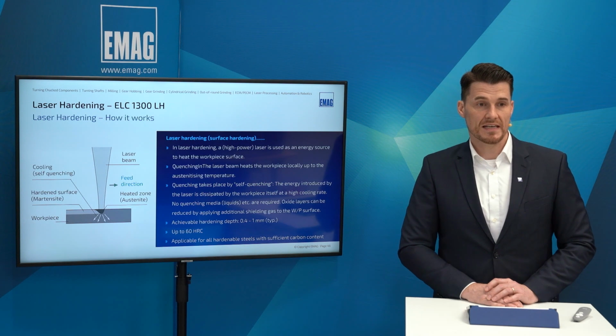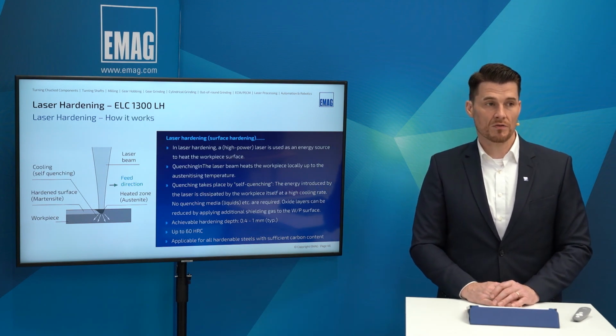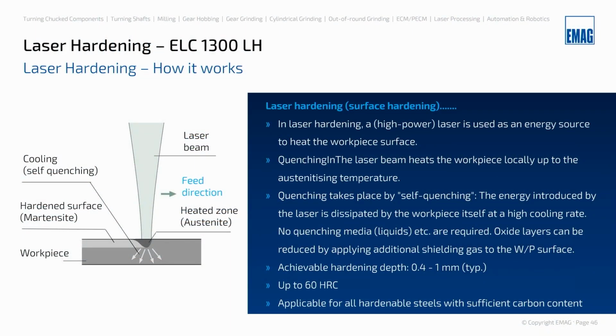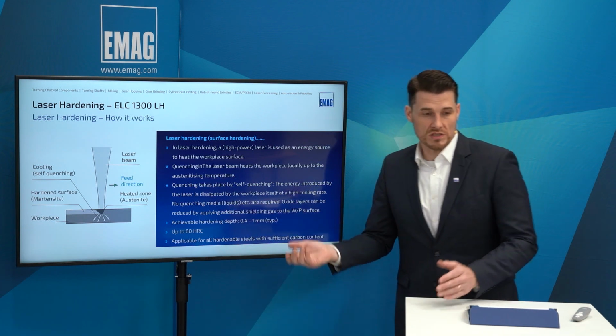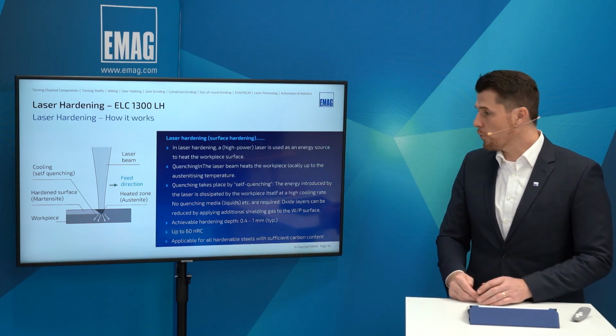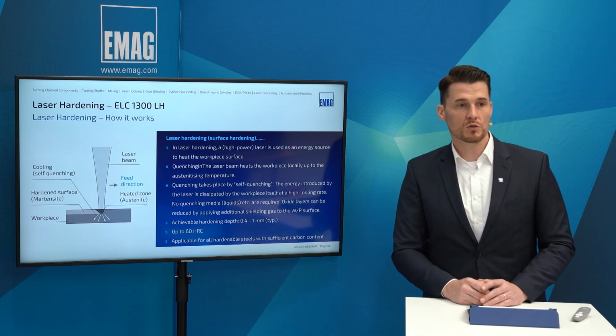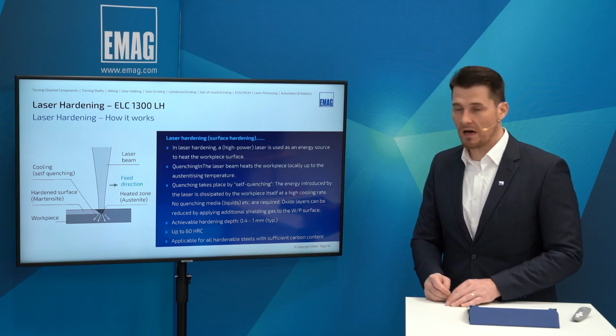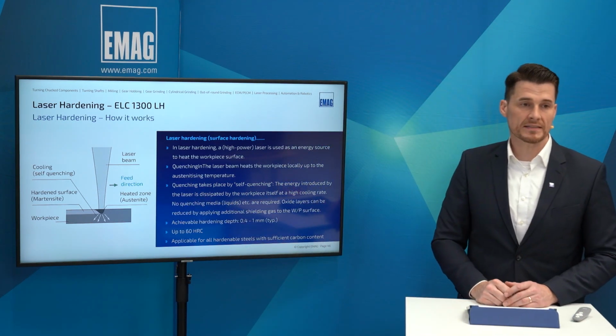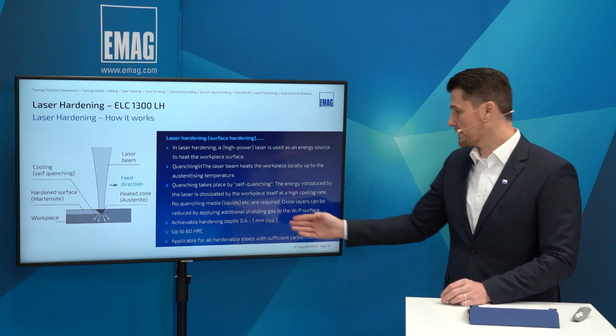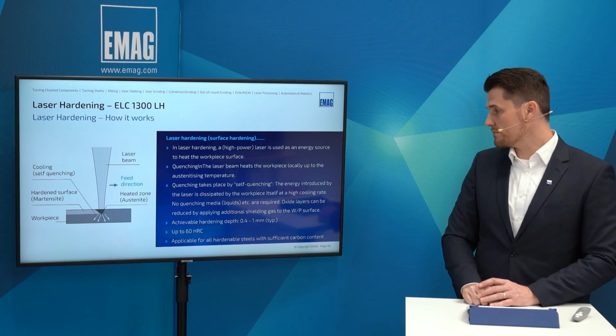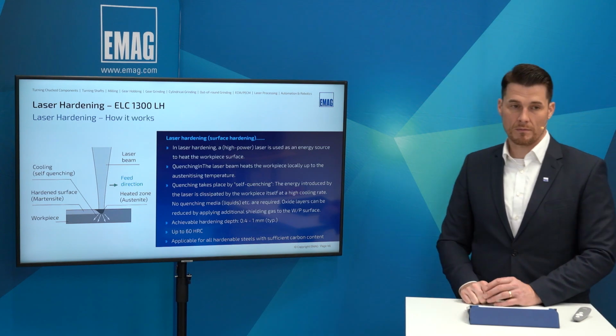Coming back quickly to the laser hardening process itself, what happens? Again, we move a laser beam across the workpiece surface. You see the feed direction here, and rectangular to the feed direction, the laser energy is scanned back and forth. That way a track of a width of 10 to 30 millimeters is being hardened. So the heat we put into the workpiece leads to the structure of the material changing to austenite. This is just like in the normal hardening process. Now what is different? The workpiece itself is cooling down, and that cooling is enough to do the quenching. So after this cooling down, you immediately reach the intended hardened surface, meaning a martensite structure. Typical values are, like we said earlier, 0.4 to 1 millimeter is possible maximum, and up to 60 Rockwell can be reached.